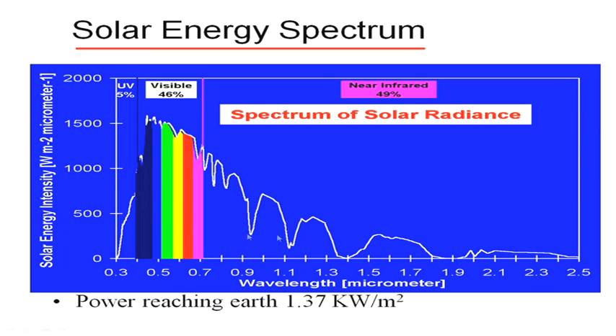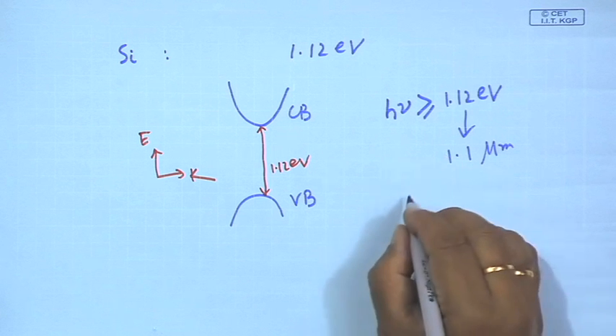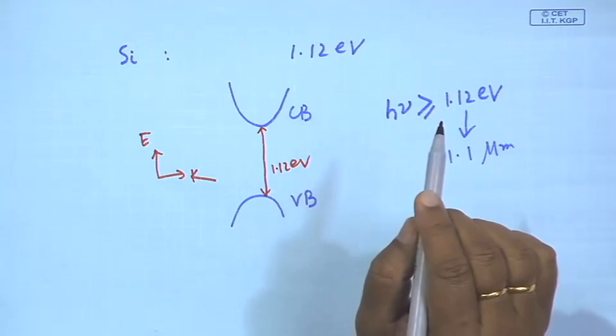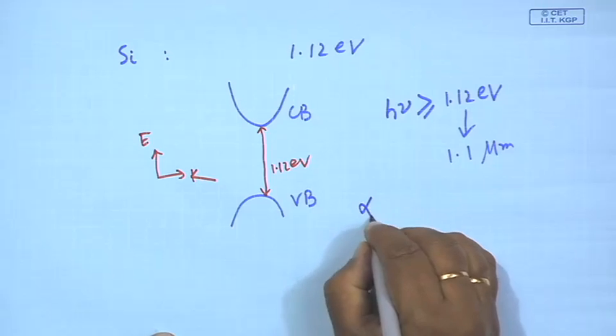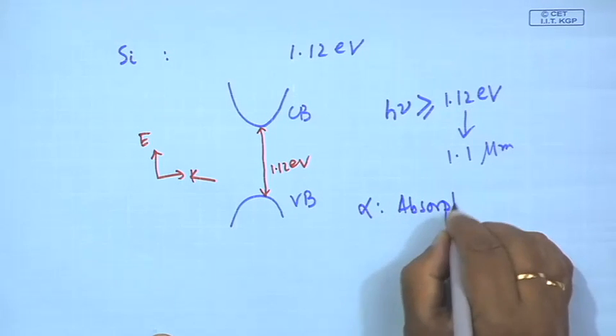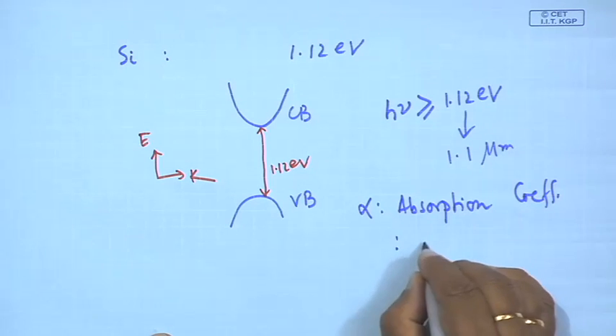So theoretically most of the solar spectrum can be absorbed by the silicon, and unfortunately for silicon the absorption coefficient is very small within this region of the wavelength which it can absorb. So consequently, though theoretically a large portion of the solar energy spectrum can be absorbed by silicon material, unfortunately because of its low absorption coefficient, the electron hole pair generation on absorption of the solar energy over silicon is very less. And another important aspect of silicon is that it has an indirect band gap. Band gap is 1.12 electron volt, and it has the absorption coefficient, alpha, which is small, low.